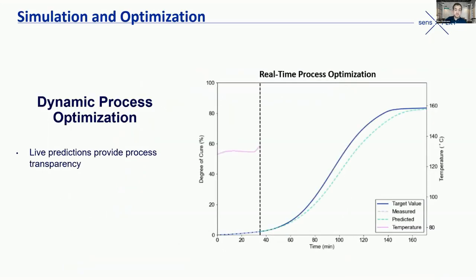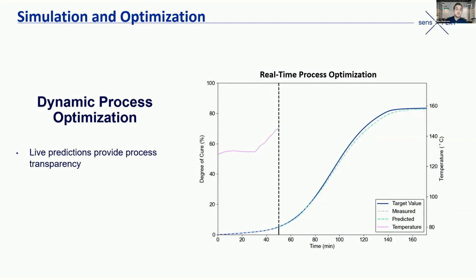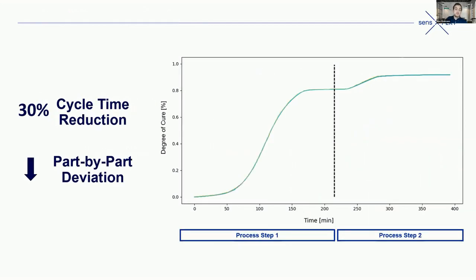We're kind of doing that same process I showed before, where the temperature is that pink line, and we can make dynamic process optimizations here by just adjusting that temperature. We can increase that degree of cure, make sure it hits the target. And really the end result is we just are able to guarantee a really consistent manufacturing process part by part. Because of that part by part deviation being so much decreased, we can actually reduce that cycle time. So in this case, we were able to reduce the cycle time by 30%, just because we knew we were hitting that target degree of cure in that first process step every time. We didn't need those really long hold times.